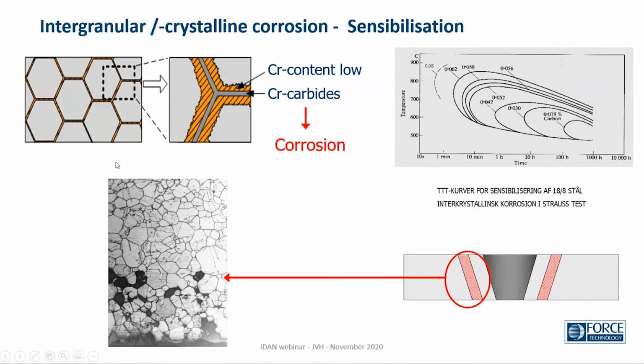I mentioned intergranular or intercrystalline corrosion and sensitization, and it's something related to the carbon content of the stainless steel. If the carbon content is too high, heat from welding might cause precipitation of chromium carbides, and they will form on the grain boundaries, because it's easier for carbon especially, but also for chromium, to diffuse on the grain boundary. So it's easier to get enough chromium and carbon to form carbides. But when you drag chromium into carbides on the grain boundaries, then you might risk that there's not enough chromium left to secure the corrosion resistance in the areas along the grain boundaries. So that gets sensitive to corrosion.